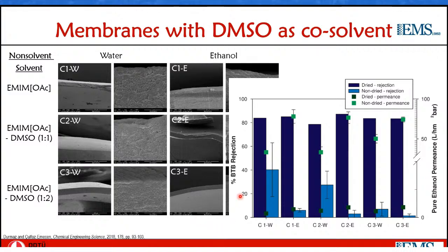When we look at the performance of the membranes in terms of, again, the bromothymol blue rejection and ethanol permeance, when the membranes were dried, as you see in the dark blue bars and the dark green squares, the performance of all these membranes was almost the same for the 6 membranes that I show. However, when the membranes are used without drying, they're not only lower than their dried counterparts, as I've also mentioned earlier, but there are also differences between the fabrication conditions. So when we switch from water to ethanol as a non-solvent, or when we increase the DMSO content of the solvent system, the rejection essentially decreases. So it seems that changing the solvent system and also the non-solvent changes the morphology of the membrane. However, when we dry all these membranes, they seem to all collapse to more or less the same structure.